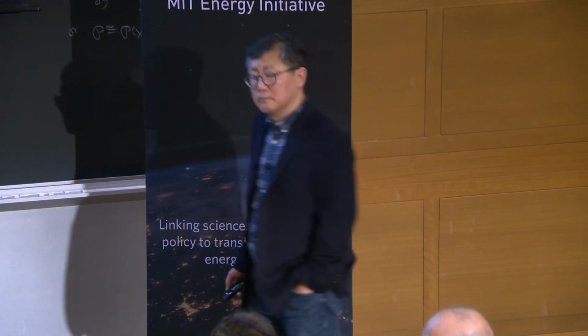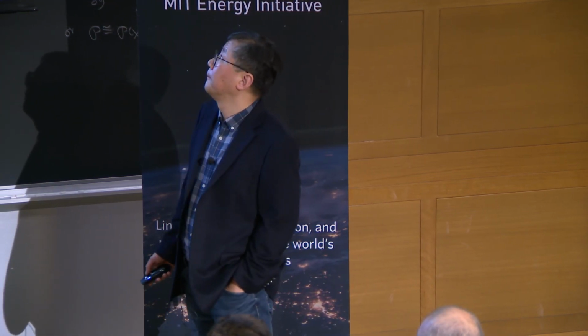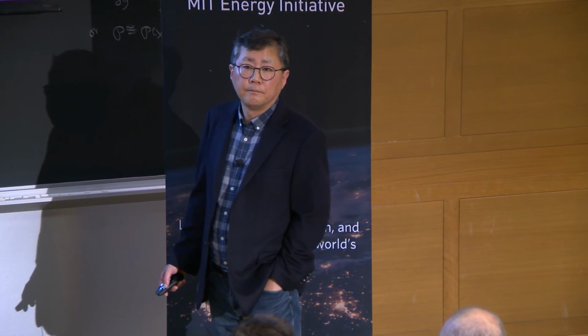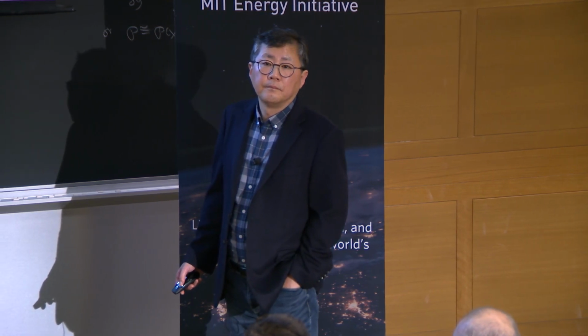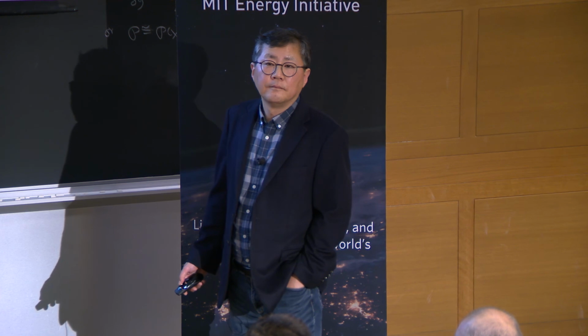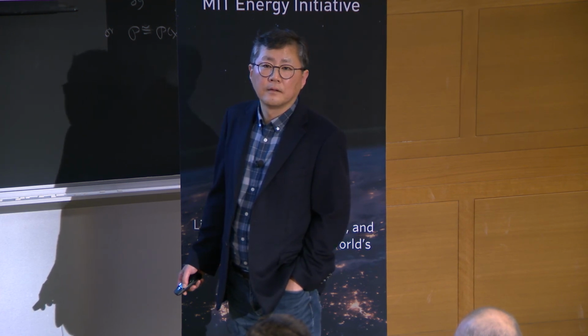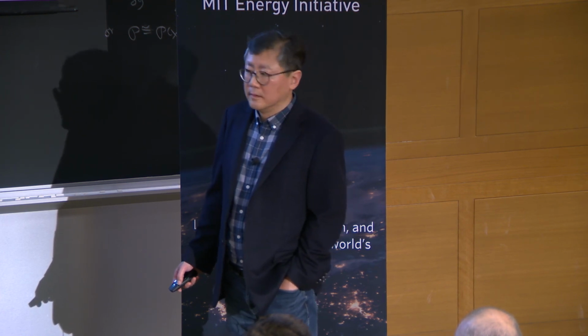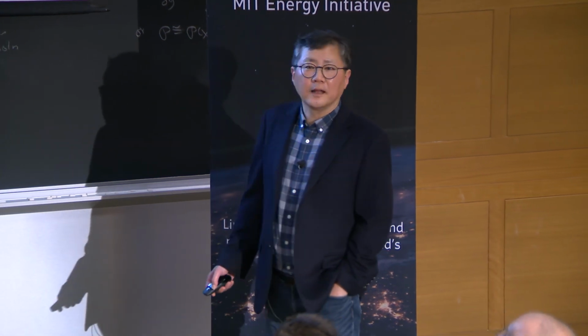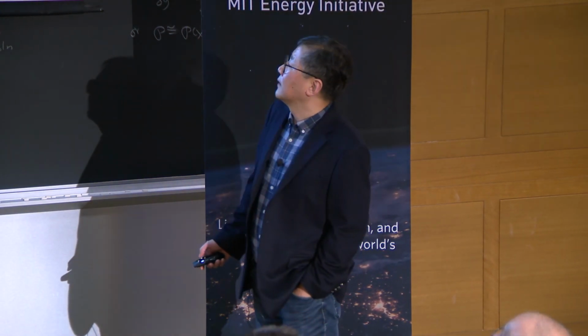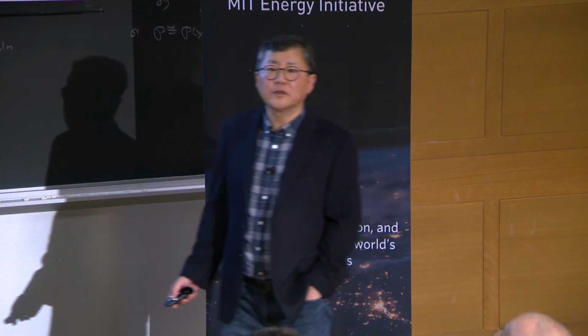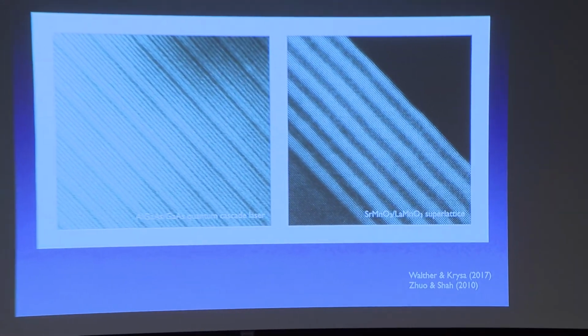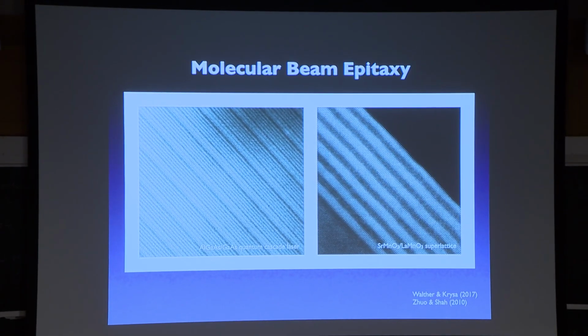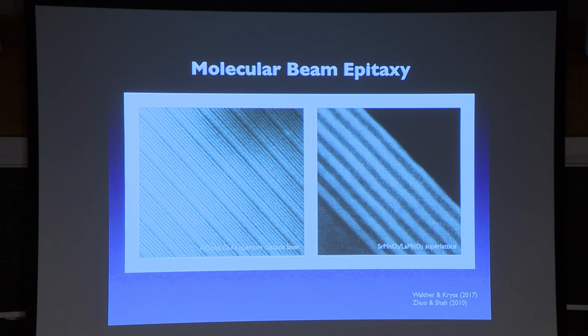I had a question about the twisted bilayer stuff. There are bulk materials, instead of 2D, just bulk materials that have hexagonal symmetries. If you grow 2 bulk materials on top of each other with a twist angle, do you also see similar phenomena? If you know how to do that, I think that you should be able to. But the thing is that, again, that was the point of this particular slide. When you grow them, bulk crystal on a bulk crystal, it is very hard to change the atomic registry between the layers, because they relax into the most comfortable configuration.